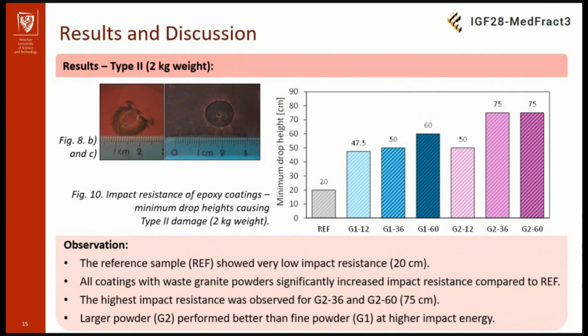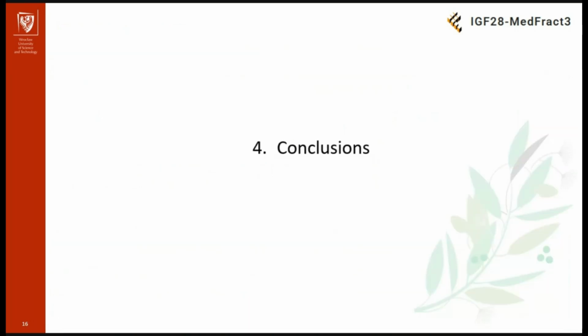It is worth noting that there is a difference between the shape of the cracking for the reference sample and for samples with granite powders. For granite powders, the damage was more regular and rounded, and for reference samples it was more irregular.